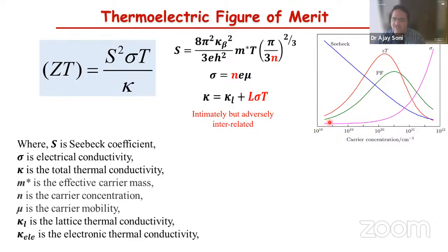Now consider the other end of the charge carriers, where the insulators are, the plastic materials or non-conducting materials. There the electrical conductivity is poor, the Seebeck coefficient is large, and the thermal conductivity is also poor. So you cannot have insulators as good thermoelectric materials either. You need a material which has an optimized value of the charge carriers, and these are the narrow bandgap semiconductors, which are good for thermoelectric research where the charge carriers are optimized.